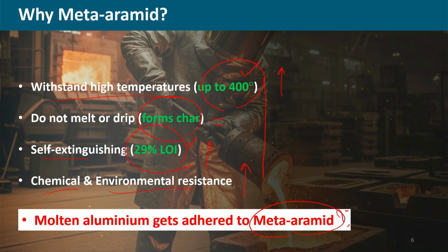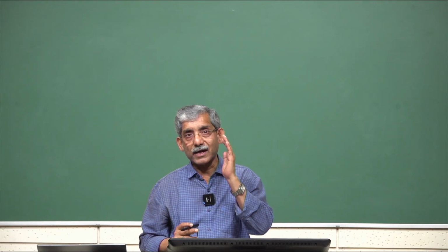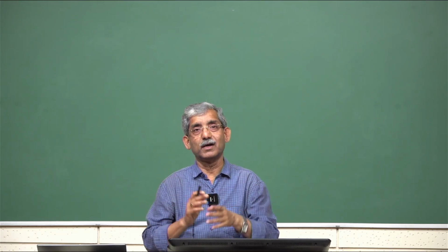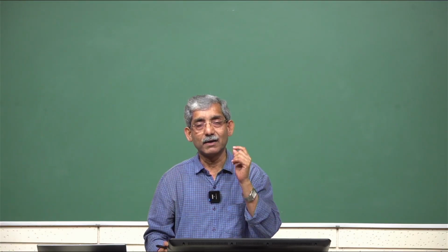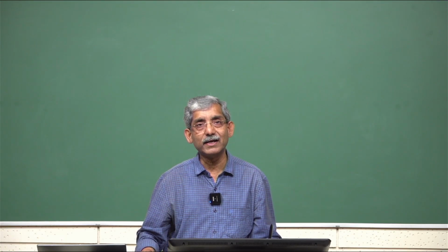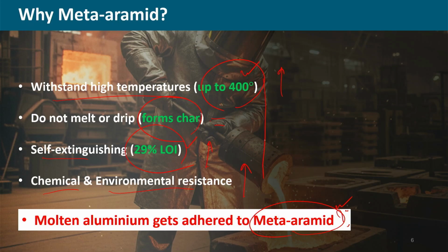But the advantage which wool has is that molten metal does not stick to the surface, but in case of meta-aramid, molten metal sticks to the surface. So, our approach was to use the positive points of both the fibers. Wool has the advantage that it is comfortable in nature due to high moisture absorption. So, we tried to use the positive attributes of both the fibers and develop clothing of blended yarn, blending of meta-aramid with wool in different proportions.